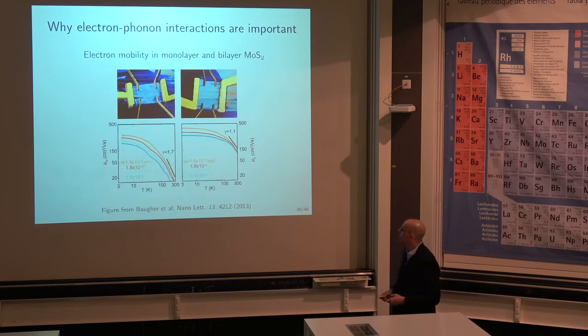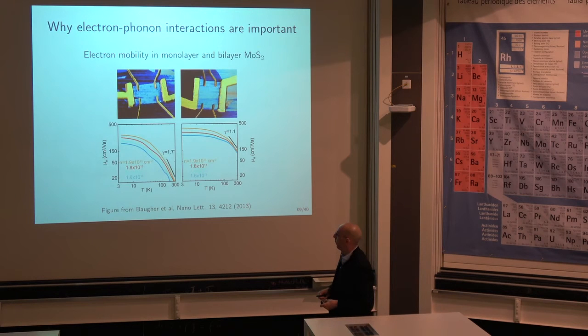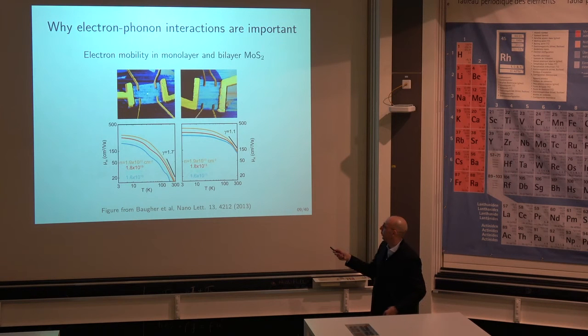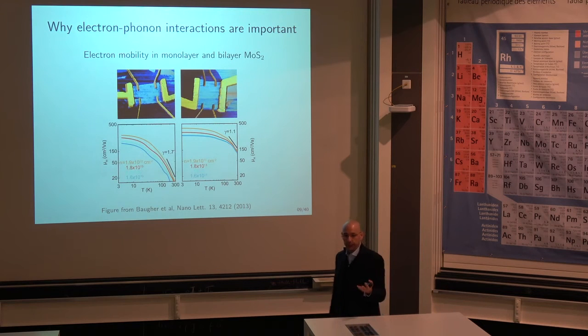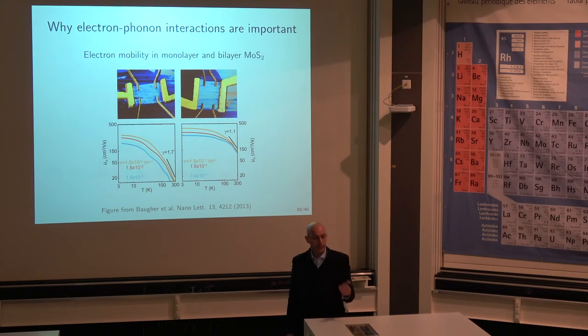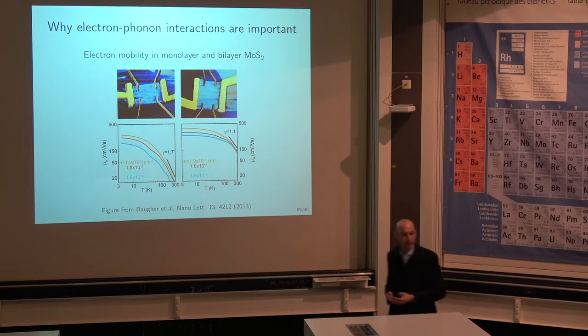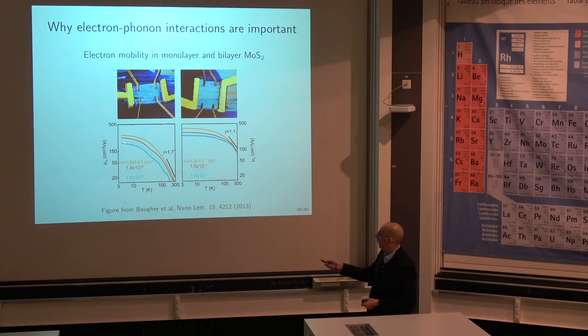phonons around. Second example, probably this is more familiar to the Department of Materials here. This is measurements of electrical transport on 2D materials. That's monolayer molybdenum disulfide, and this is bilayer molybdenum disulfide. And the quantity here is the mobility. The mobility is the coefficient of proportionality between the average velocity of the electrons and the applied electric field, okay, in a simple description. What you can see here is that the mobility depends quite strongly on temperature. It changes by about 2 orders of magnitude if you go from 0 Kelvin to 300 Kelvin, so room temperature.